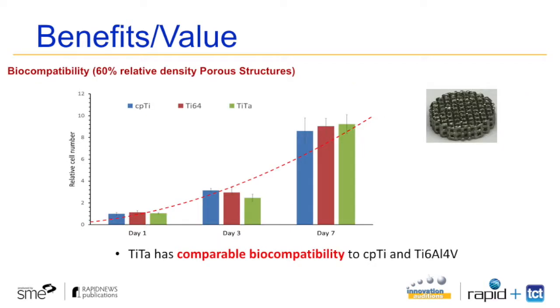And of course, since we are targeting biomedical devices, we have to do a simple biocompatibility test using osteoblast cell lines, and we observe similar, comparable biocompatibility of these new alloys compared to the commercially available material, which gives us potential to actually create this new material for specific medical devices. And there is already demand in the market for this material, and we are in talks with several hospitals and implant manufacturers to bring this innovation one step closer to the market.